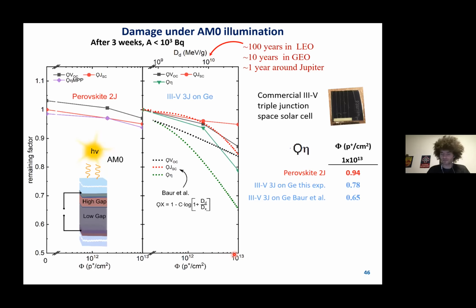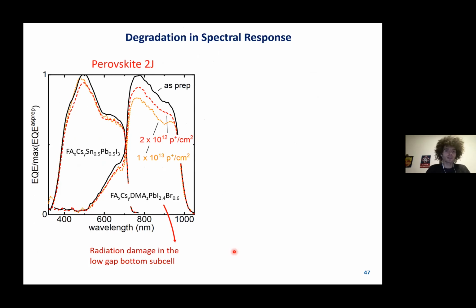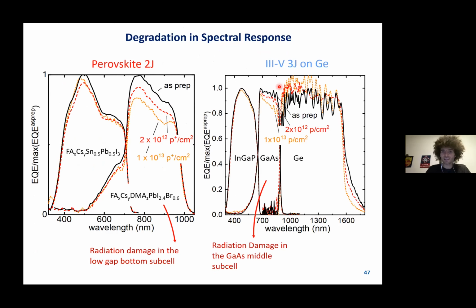All right. So now let's try to find out what is degrading in this perovskite tandem. The first thing, of course, is doing EQE, right? And when doing that, we see some damage in the low gap subcell of the perovskite tandem. You can measure also the EQE of the III-V triple junction. And in that case, it is mostly the gallium arsenide middle cell which degrades here.